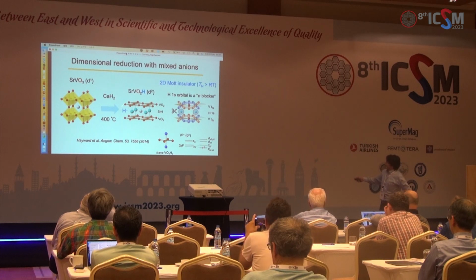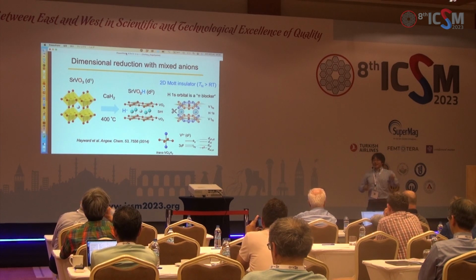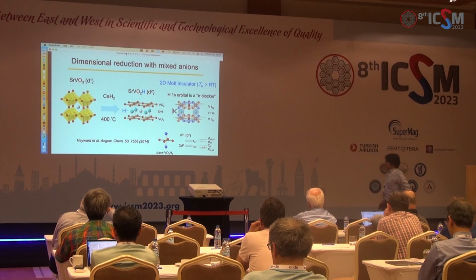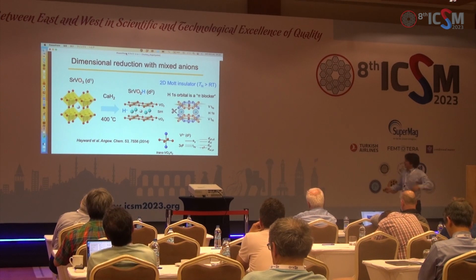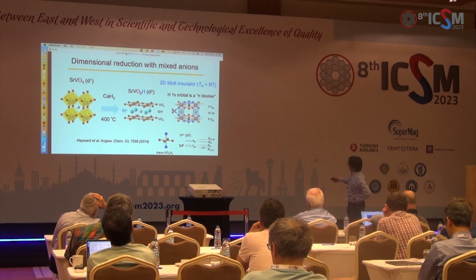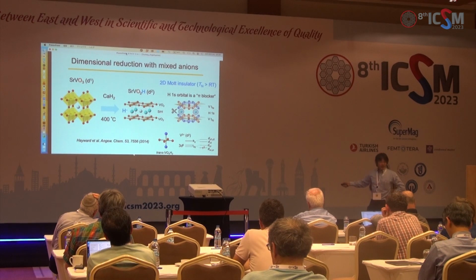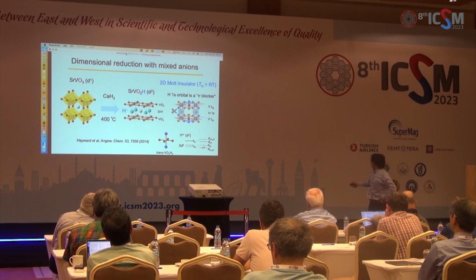But you may think that this is just a three-dimensional structure, just the change of the anions, and the three-dimensional corner-shared structure is retained. However, when you consider the chemical bonding and molecular orbital configurations, you see that this is electronically two-dimensional. Once again, the crystal structure is just three-dimensional; we started from the three-dimensional perovskite. But when you look at these orbitals, along the c-axis, namely this is the t2g orbital. This trans configuration gives rise to the further splitting of the eg and t2g states. As I said, there are two electrons located in these dxy and dyz orbitals.